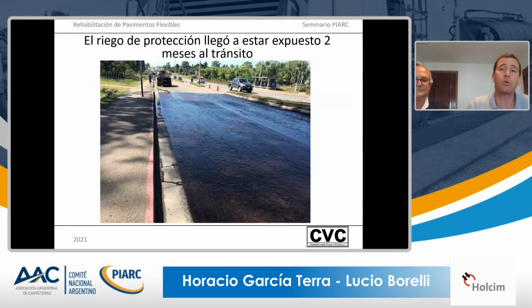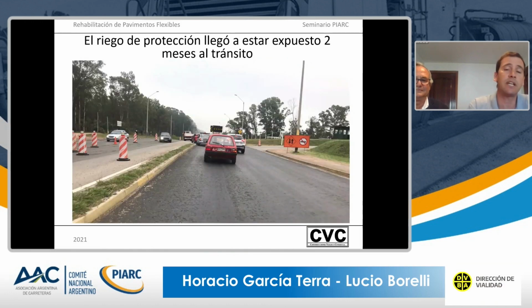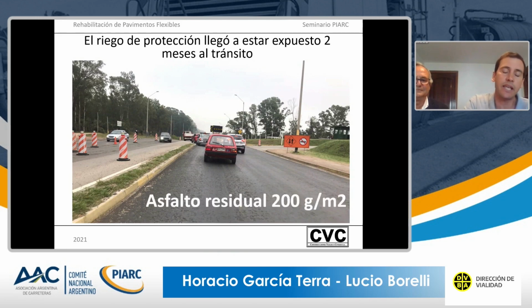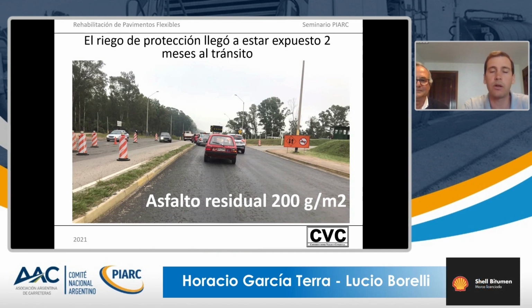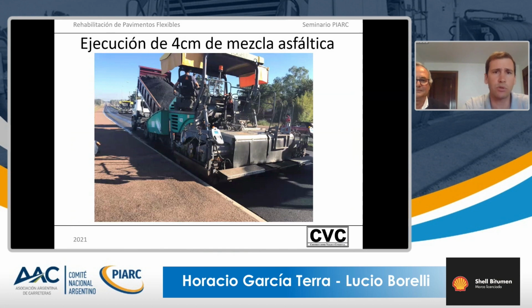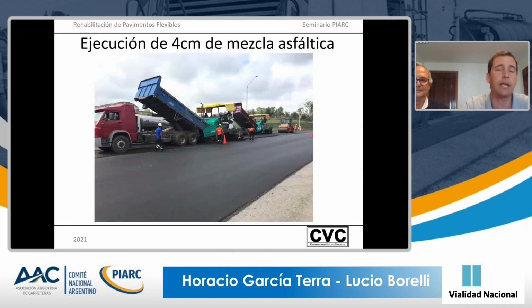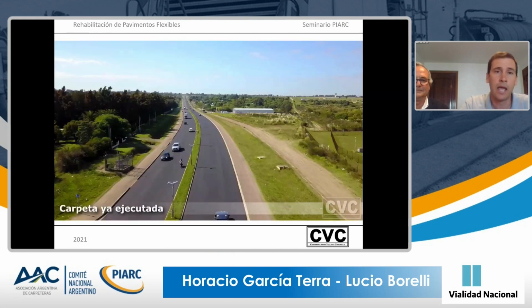And then we need to do protection irrigation, and in the case of Road 102, it was exposed 2 months to traffic with those 22,000 vehicles a day. And this irrigation of 200 grams per square meter should be done twice by irrigating 1 liter of diluted solution. Then we also did 4 centimeters of traditional asphalt mixture, taking all the precautions required with this thickness.